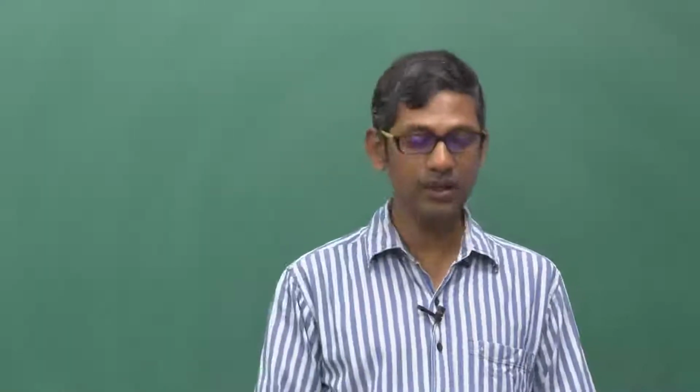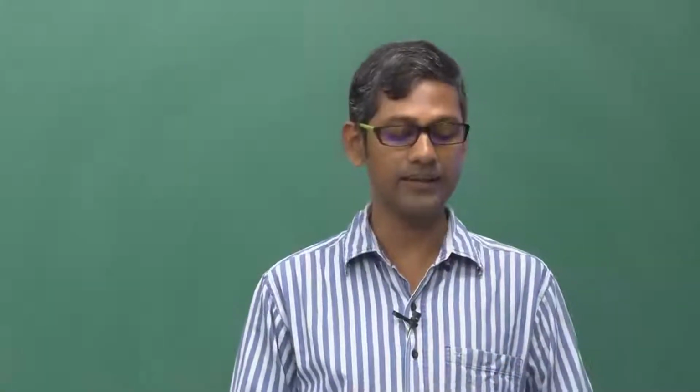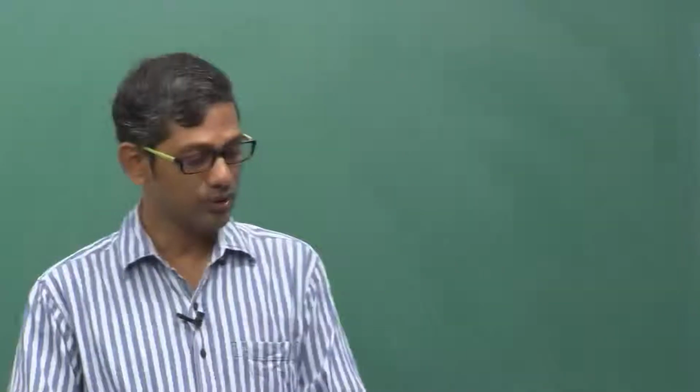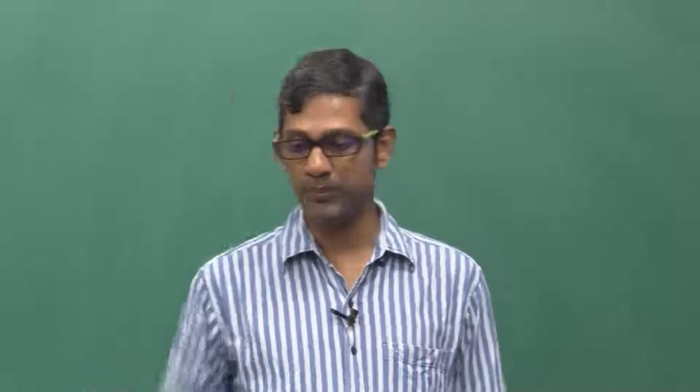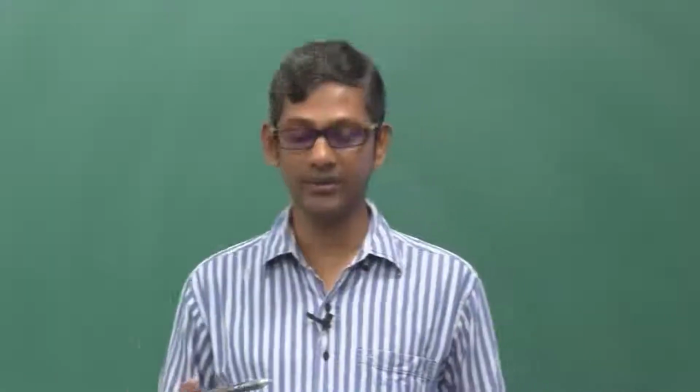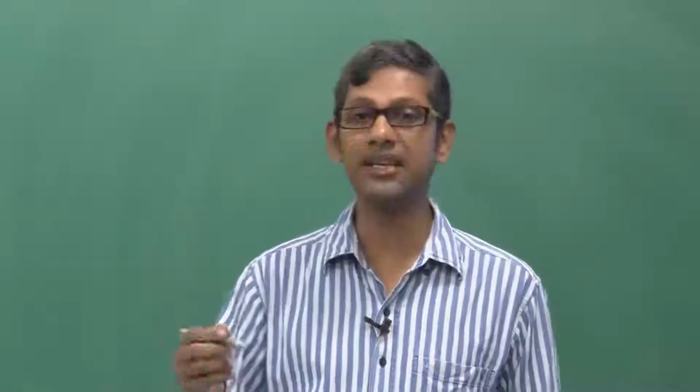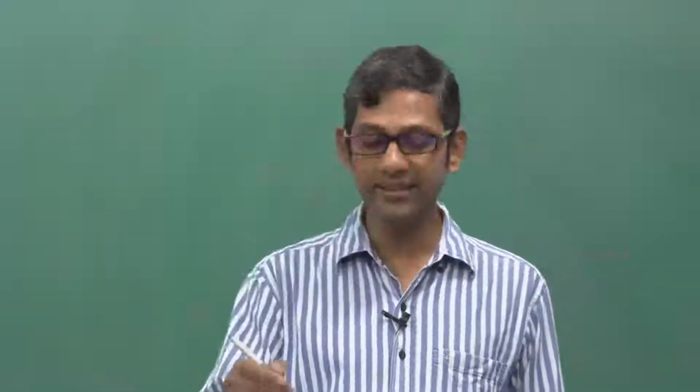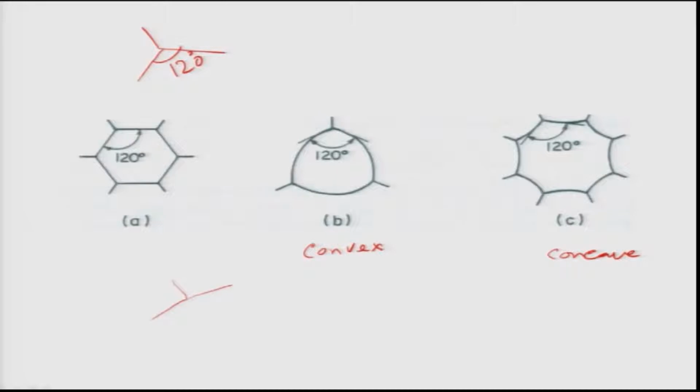So now let us use this analogy to explain the grain growth mechanism here. It's not very difficult to understand, as now I have given you the whole concepts. So what? As you know, if I have grains with sides less than 6, these grains will have a convex curvature. So that means the grains will slowly shrink. Why? Because r will keep increasing if this boundary moves to the center. Then all the grains which have fewer than 6 sides will slowly vanish.